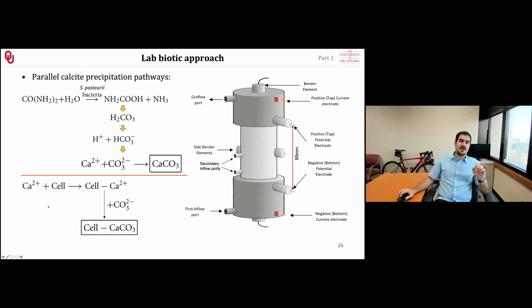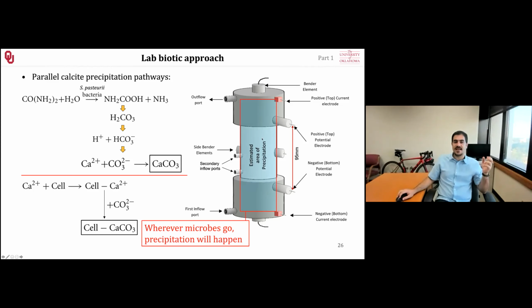But there is a benefit to these microbes as well. They tend to attach to these calcium ions. The calciums actually get attached to the body of these microbes. So as they move around inside the column to find food, because they're hungry, they take these calcium ions with them, and wherever they go, they decompose urea, they produce carbonate, and at the same time, calcite gets precipitated. So we have a better distribution of the cementation inside our sample or under the ground using these moving microbes. We call them motile microbes.